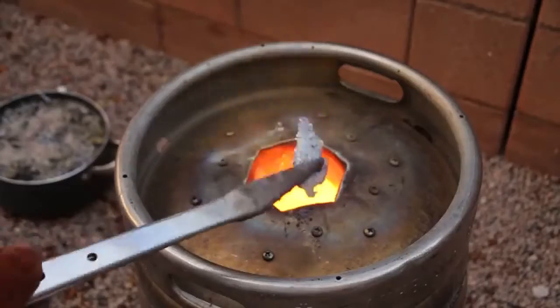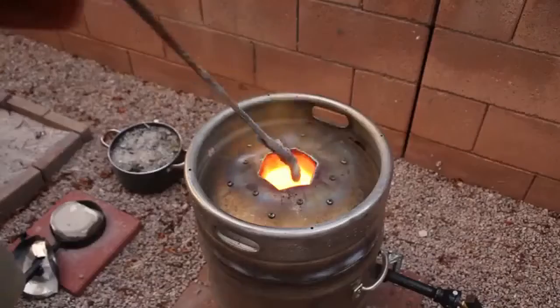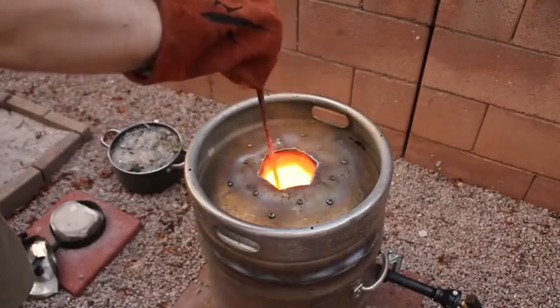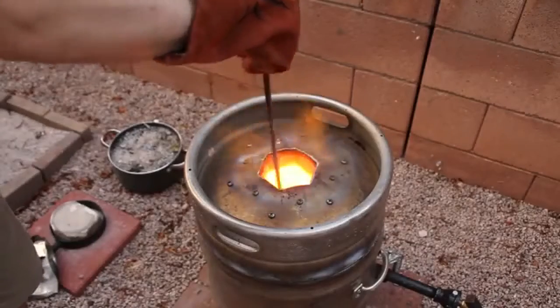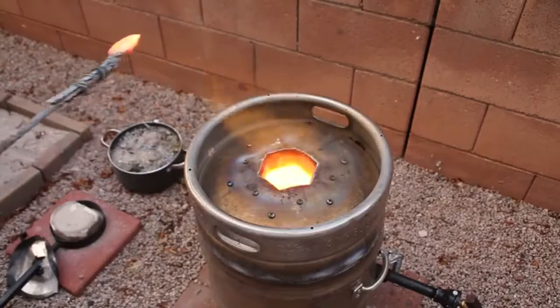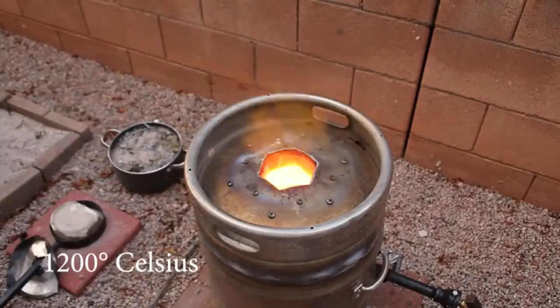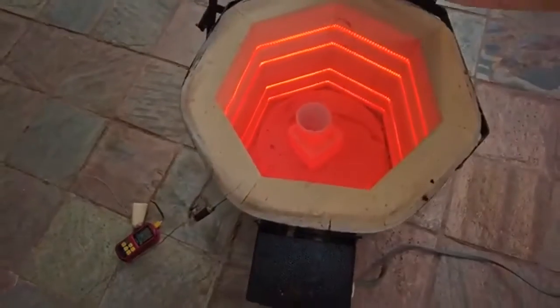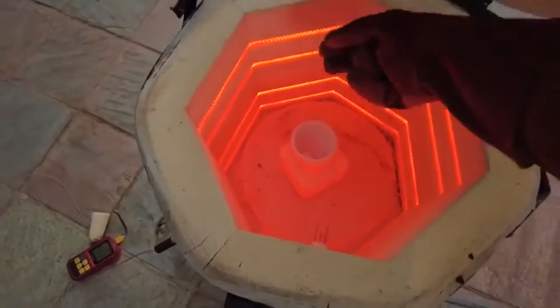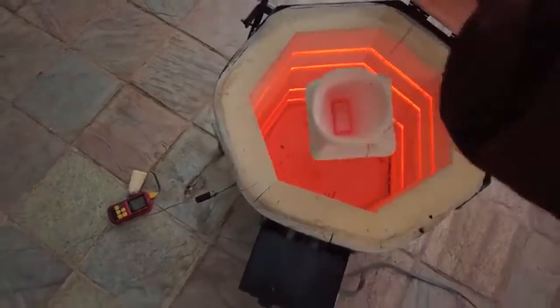Once the metal was melted, I added a small piece of aluminum to add strength and improve the corrosion resistance of the bronze alloy. I let the bronze heat up to about 2200 degrees Fahrenheit to make sure that it was liquid enough to fill the thin walls of the mold. Then I removed the shell from the kiln and poured in the metal as quickly as possible.